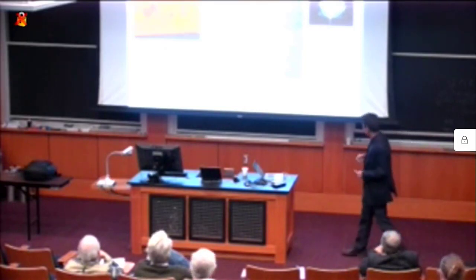So let's try it. We've taken a particular perovskite. This is not really relevant for these details. We've made these membranes, put it on a TEM grid, and lo and behold, you have a nice lattice. You can see the ordered arrays of these atoms. And the statement would be, in summary, that when this membrane is 5 crystallographic unit cells thick or thicker, it's all basically a nice crystalline membrane.